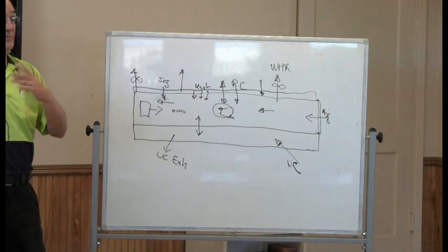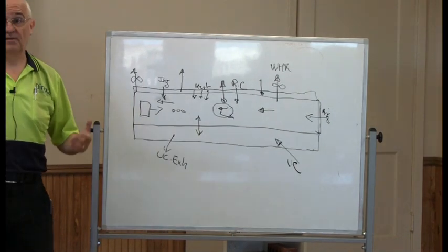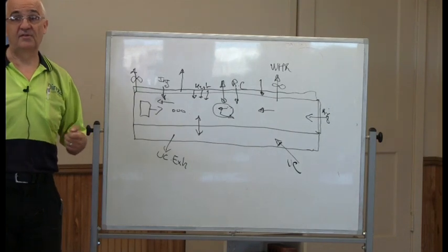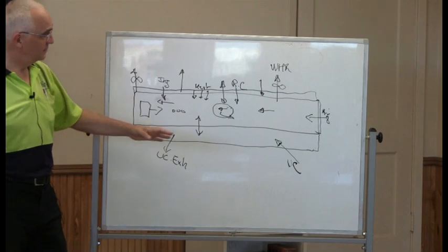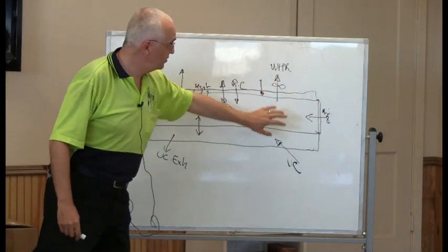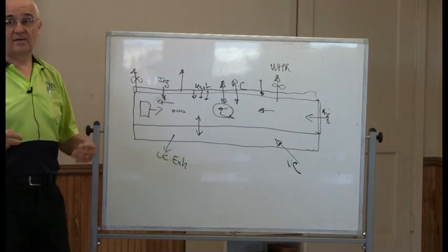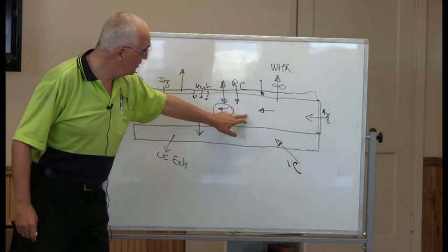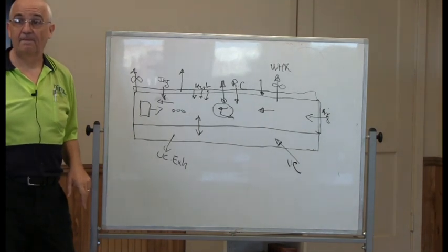And basically what I've been doing Monday with the pitot tube, with the anemometer, etc., is measuring velocities to calculate mass of air, and then to compare each of the spots, and basically extrapolate how much air I have through my process.